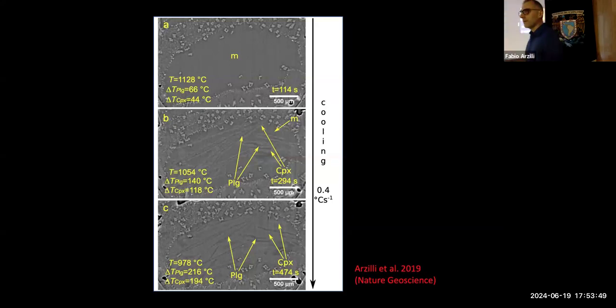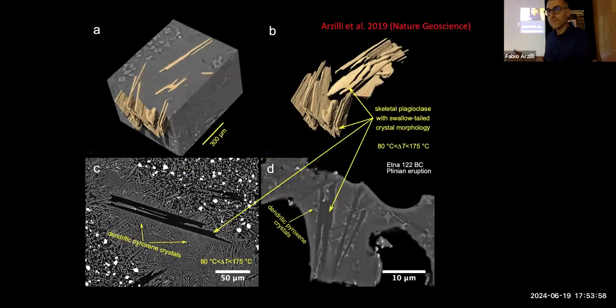So when the system is perturbed fast, so the undercooling is increased fast, crystallization can react fast. And this is what we observed in 3D. So we produced this swallowtail plagioclase. This is the experiment, natural Etna. Of course, our experiments went further with the undercooling. We investigated undercooling between 80 and 175 degrees Celsius. We produced this skeletal plagioclase with this dendritic pyroxene around them. Here in the natural case, you have this skeletal plagioclase and then this initial dendritic crystallization of pyroxene, but then the rest is melt. So it means that in the natural case, the natural magma didn't experience very extreme undercooling conditions.